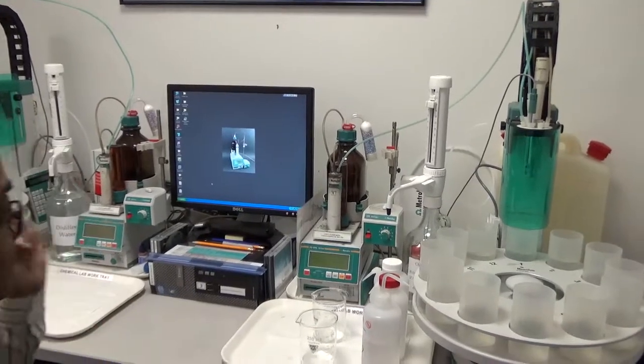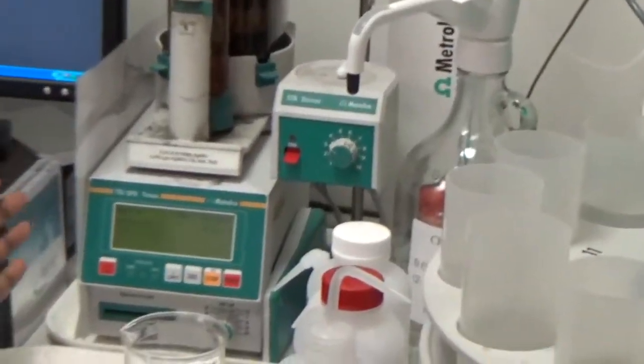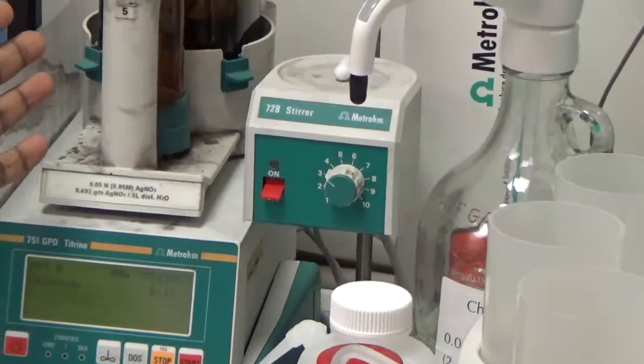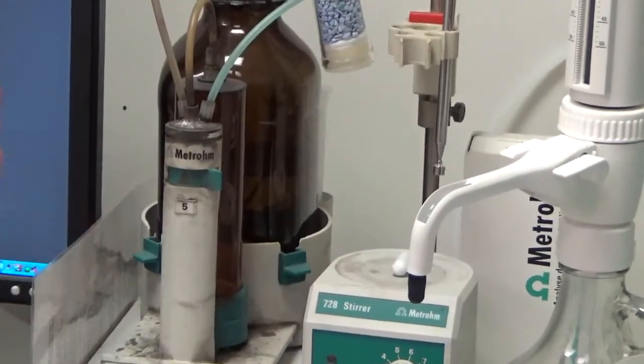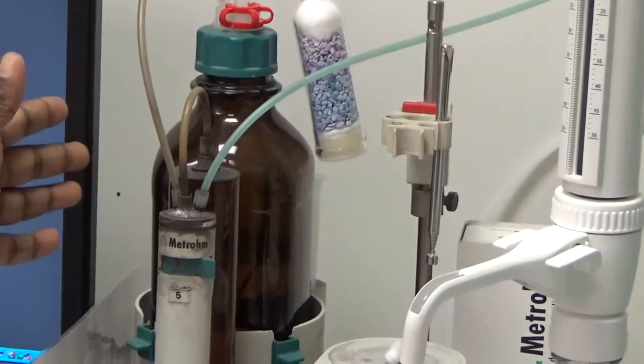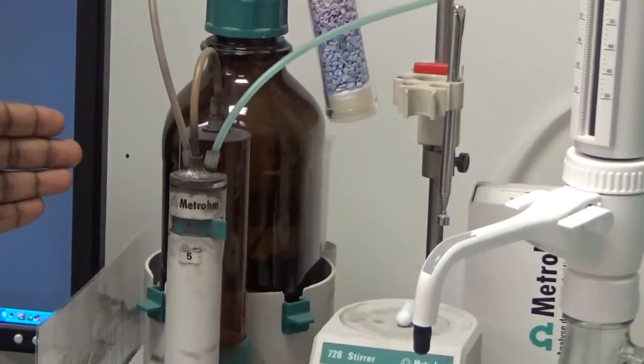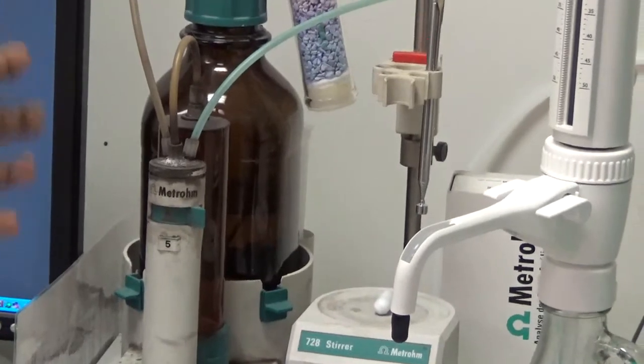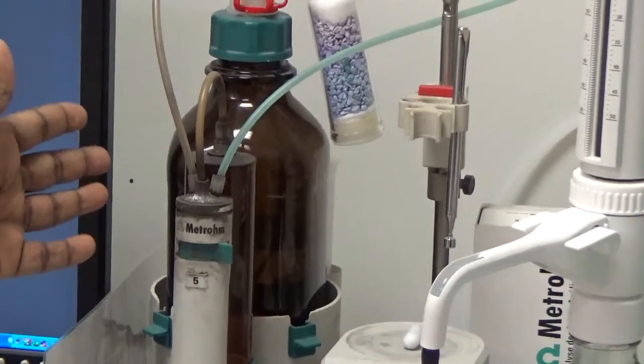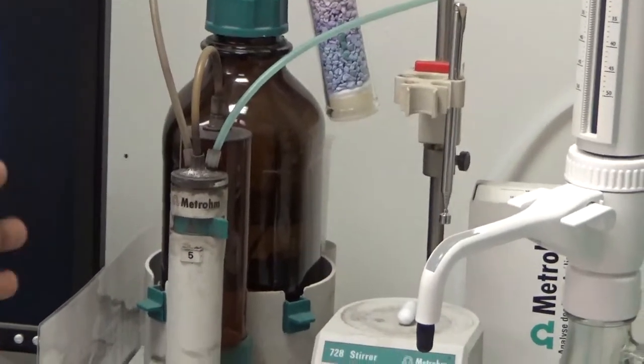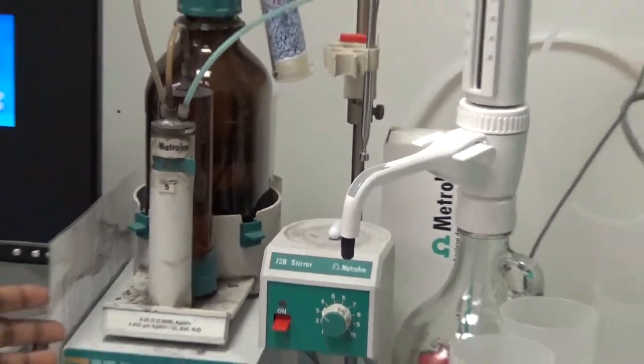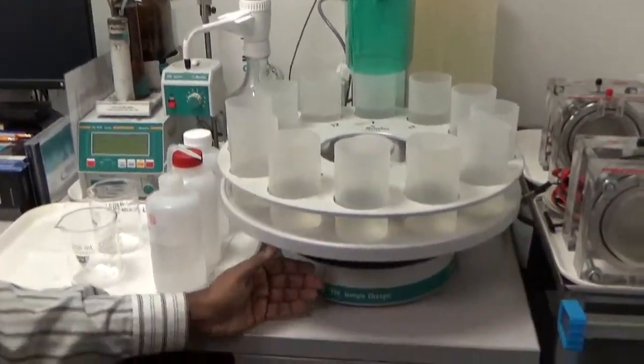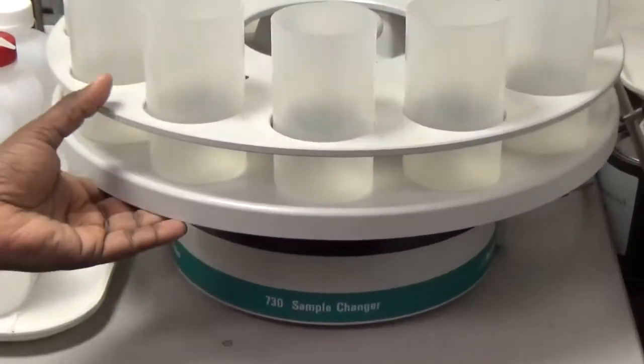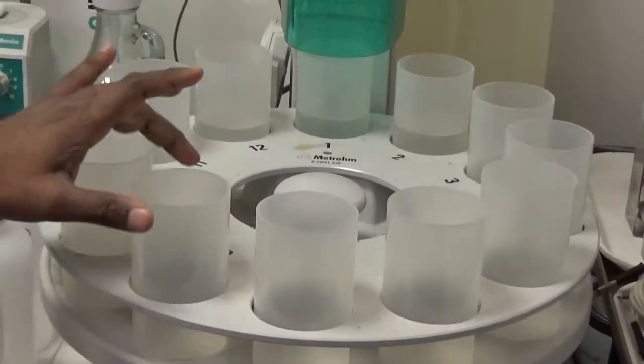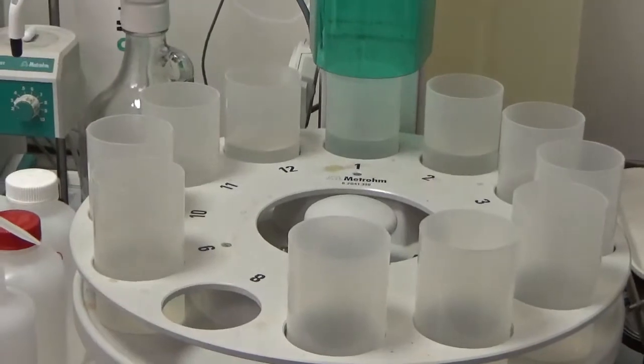This is a Metrohm setup. We have a Metrohm 751 GPD Titrino with a 728 stirrer, and we use a 5 milliliter exchange unit which has an amber glass bottle to contain the silver nitrate titrant. We have to use amber glass to prevent precipitation of silver, and that's why we have the silver nitrate in the amber bottle. Then we attach the 751 Titrino to a 730 sample changer, and the 730 sample changer comes with a 12 position sample rack where we put the plastic beakers from Metrohm. These are 250 milliliter beakers.